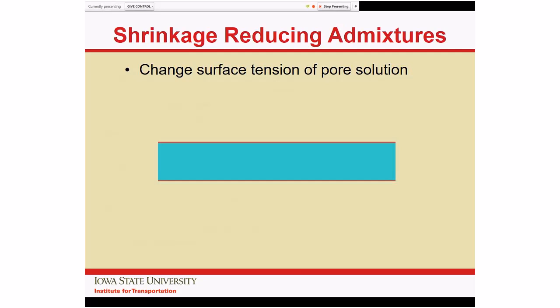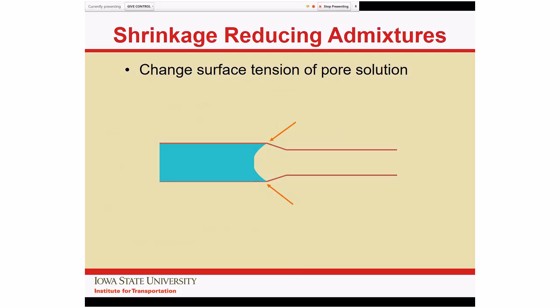All right, the next thing we were looking at is the idea of shrinkage-reducing admixtures. These are chemicals that change the surface tension of pore solution. And this is important because when a capillary pore is drying out, it has a fairly tight angle of surface tension, and so the force will tend to close the pore down, and that's what's basically fundamentally driving the shrinkage within the system. And so if the pore is full of water, it's pretty big, but if it's dry, it's pretty small, and hence we have the shrinkage. By changing the angle of contact between the solution and the pores, you can actually change the amount of shrinkage that occurs.